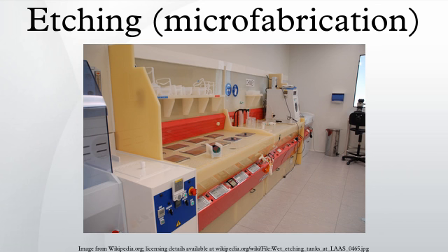The authors employ multistream laminar flow that contains etching and non-etching solutions to fabricate a glass groove. The etching solution at the center is flanked by non-etching solutions and the area contacting etching solutions is limited by the surrounding non-etching solutions. Thereby, the direction of etching is mainly vertical to the surface of glass. The SEM images demonstrate the breaking of the conventional theoretical limit of aspect ratio and contribute to a twofold improvement.